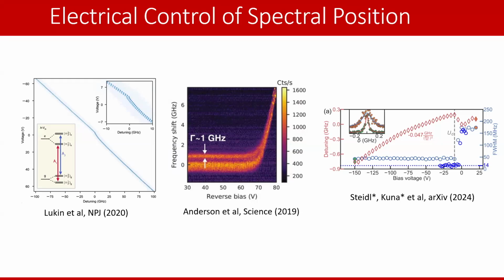And actually, this comes from the optical light shuffling the moving charges around. If you imagine just having this thing sit there in the dark, it will stay in the same position, because it's down at 4K and the electrons and holes don't move around that much. But as soon as you add the optics to do the optical readout of the spin states, then you start shuffling things around because of the energy from the photons. And that's no good.